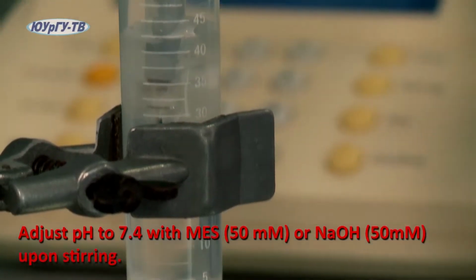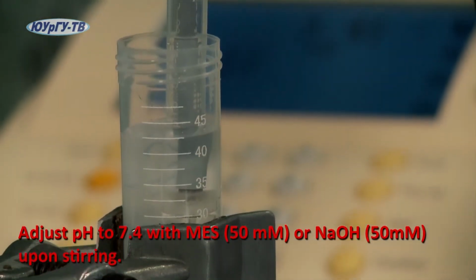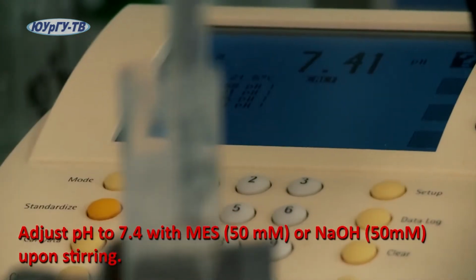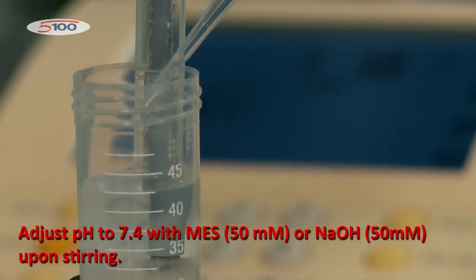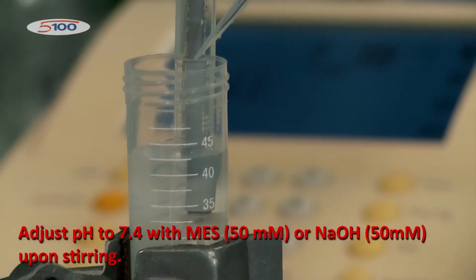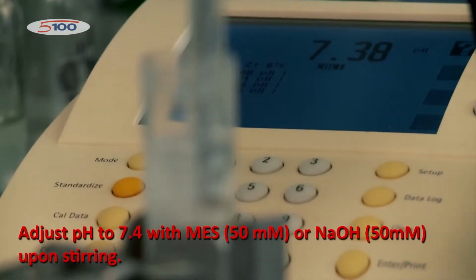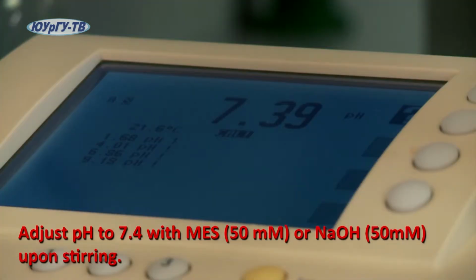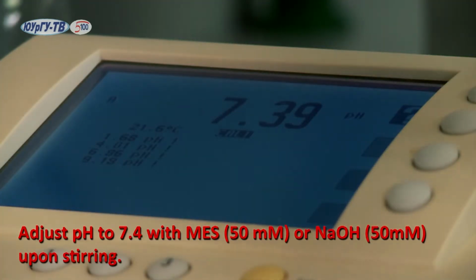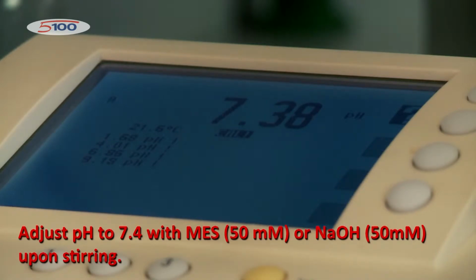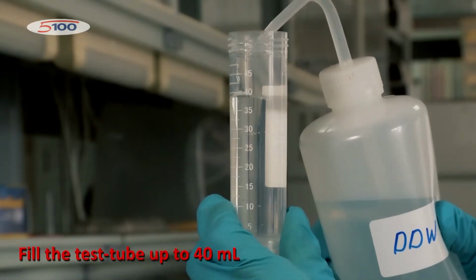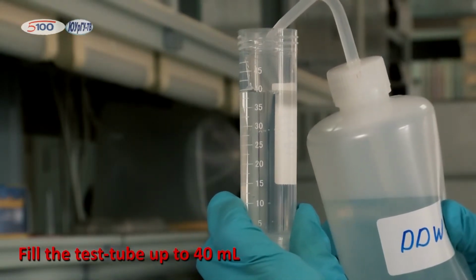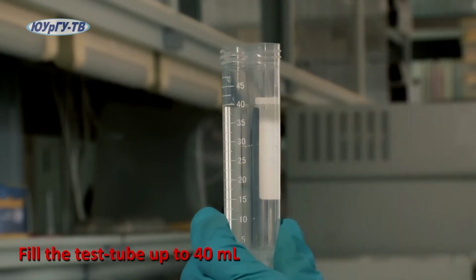Adjust the pH of the pre-dissolved solution of dipeptide to 7.4 by cautiously adding solution of MES or sodium hydroxide to the dipeptide solution upon stirring at room temperature, and monitoring the pH with a pH meter. After adjusting the pH, fill the test tube with double distilled water up to 40 ml to make the final concentration of 16 millimolar.